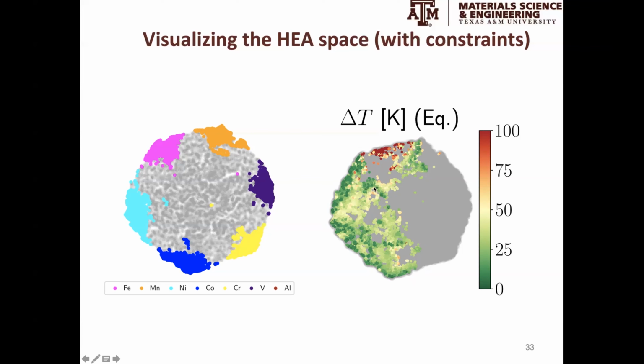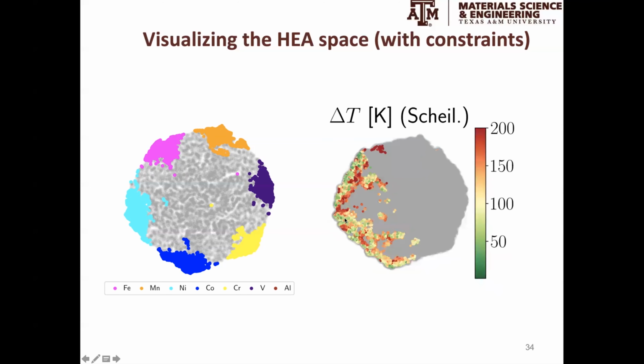But if we just focus on the FCC alloys — alloys that were FCC at 800 Celsius — we see that in general solidification ranges are not that bad. They typically are less than 50 Kelvin, as per this diagram.